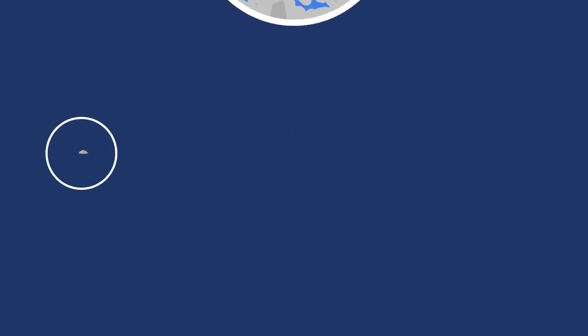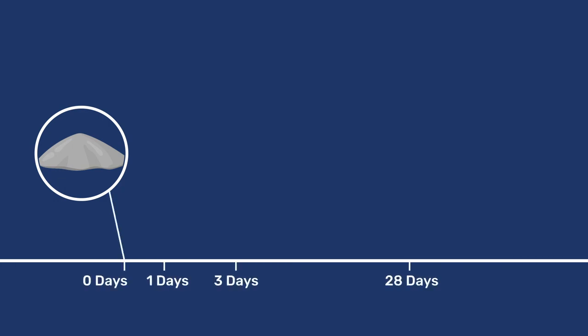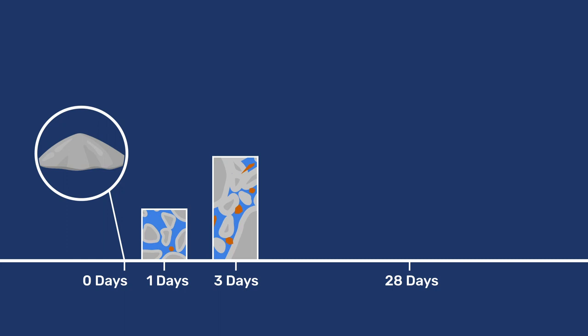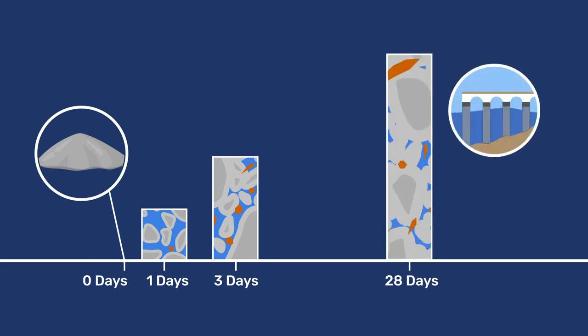One consequence of this is that after one day, concrete has already a fair strength, which is doubled by day 3 and can be related to a more extensive filling of the porosity. This strength increase continues after that, but at a reducing rate, so that to have another doubling of the strength, one must wait until day 28.